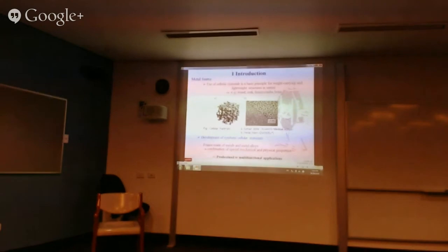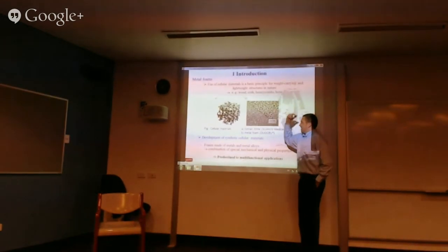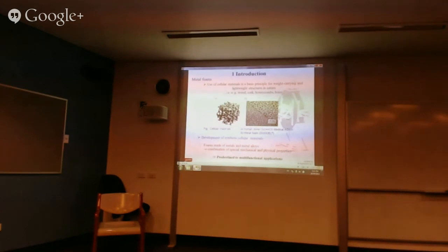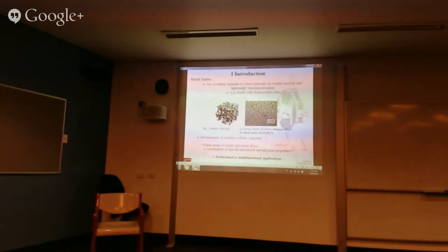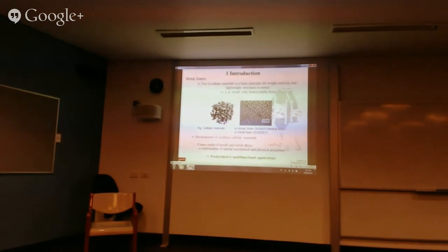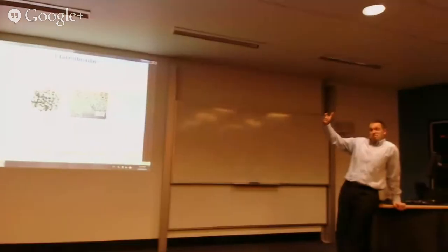So if you have an open cell structure, and if you do not use aluminium, you use, for instance, titanium, or maybe other materials, bone could grow inside, and if you go a further step, if it's an absorbable material, after the bone has grown inside, maybe the material could be absorbed. So these are the ideas of cellular materials as scaffolds for bone replacement. Either permanent, then we use titanium, or any bioabsorbable material which would be absorbed by the body after the bone has grown inside.